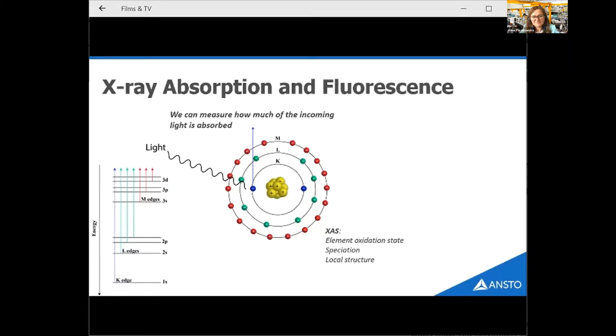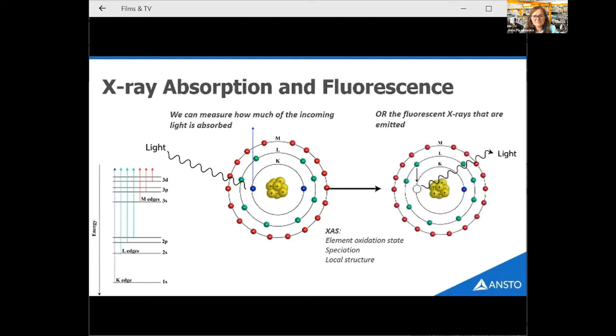And if we have the incident X-ray beam at a higher energy than the binding energy of a core electron, it can absorb and that absorption increases dramatically once you get to that energy. When that happens, an outer higher energy electron can fill that core hole. And as it does that, it emits an X-ray with an energy equal to the difference in those orbitals. And that energy X-ray is similarly characteristic for each element. These two processes are proportional. So the information that we obtain can be measured in either way.